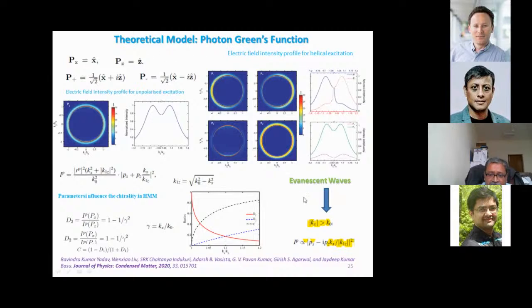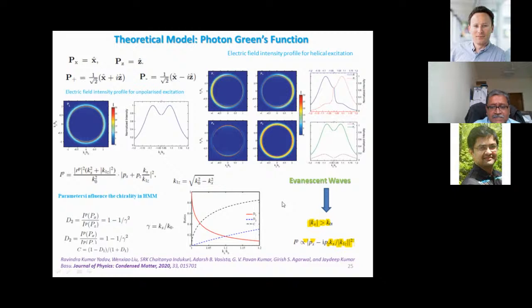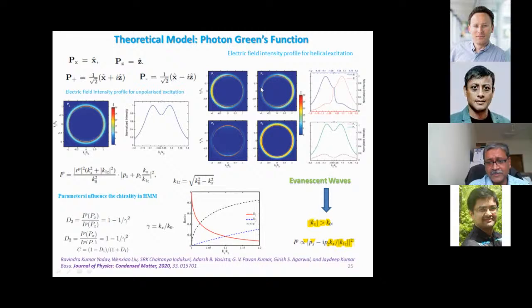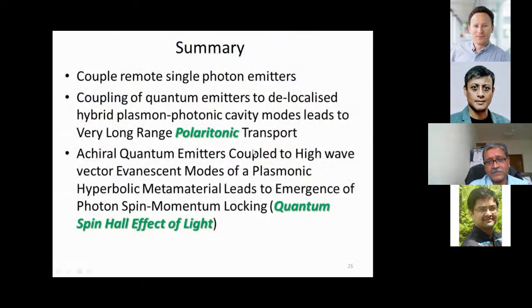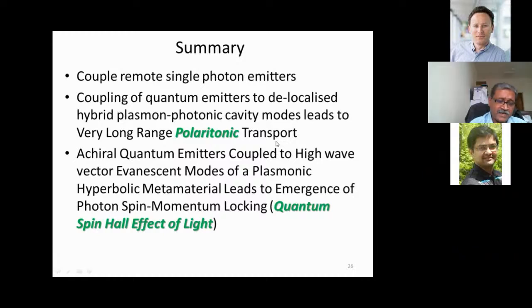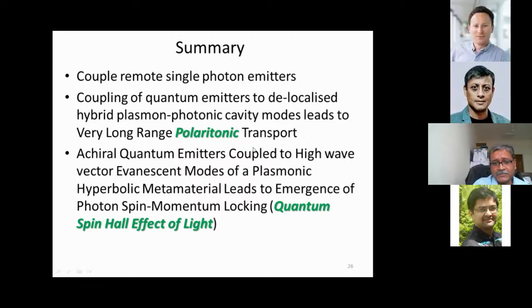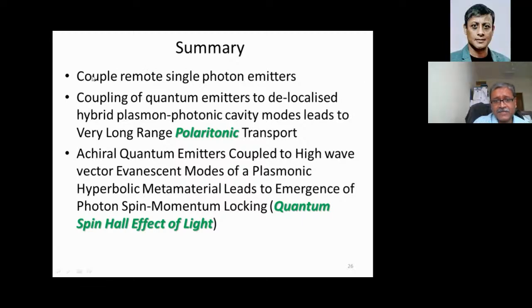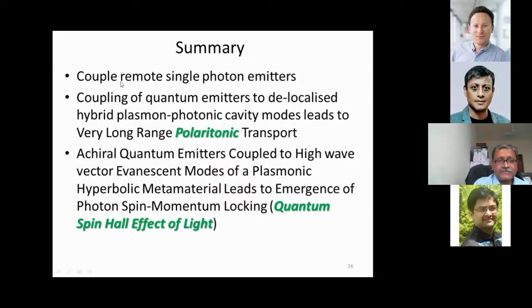Detailed in terms of the Green's function. Essentially, the long story short is that you have a coupling in the evanescent mode, the coupling of the polarization, the longitudinal and transverse components, which generates this helicity. Remember that neither the hyperbolic metamaterial nor the quantum dots have any intrinsic helicity. So it comes purely because of the coupling in the near field to this high k mode. And so I will end by summarizing that we have shown that you can couple single photon emitters.